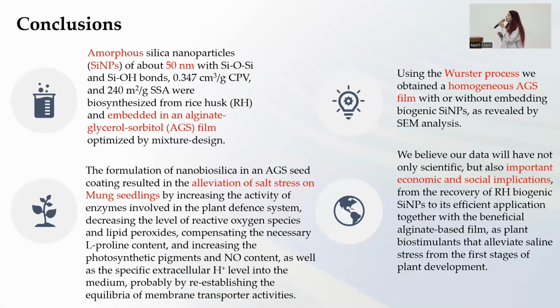So in conclusion, silica nanoparticles of about 50 nanometers embedded in an alginate glycerol sorbitol film were obtained, and this coating process was achieved by a Wurster process, resulting in a homogeneous film that also resulted in the alleviation of salt stress on mung bean seedlings.